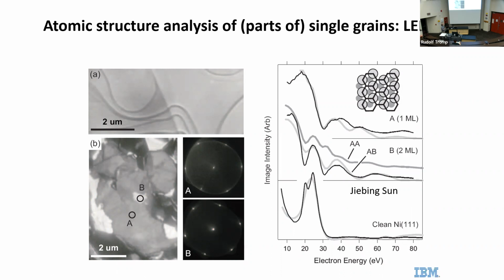So from this, we can determine the atomic structure of these films with a spatial resolution which is determined by the spatial resolution in the image, a few nanometers. So we see atomic structure within an area of a few nanometers, right, from the diffraction.